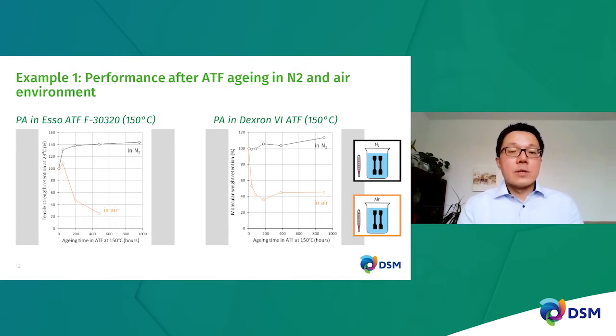here. So this figure on the left shows the tensile strength retention of polyamide aged in Esso ATF at 150 degrees Celsius under nitrogen environment or air environment. As you can see, in nitrogen environment, there is no tensile strength retention reduction whatsoever, whereas when you change the nitrogen environment to air, what you see is within 200 hours, you reach already half lifetime of the materials.